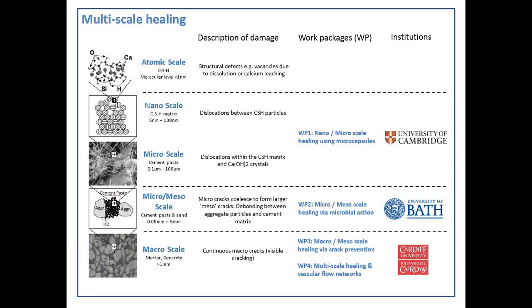So they're looking at the smaller scale using microcapsules. University of Bath are looking at the micro-meso scale using microbial or bacterial action to heal slightly larger cracks. And what we're looking at in Cardiff University in work package 3 is then a crack prevention system using shape memory polymers to restrict crack growth and to close early stage cracking. Work package 4, then also led by Cardiff University, is to combine these systems into one multi-scale healing system, and also to look at vascular flow networks as an extension of the idea of a material which is inspired by nature. So again, I'm going to go through each of these individually now, just to give you an idea of what I mean by each of the techniques.